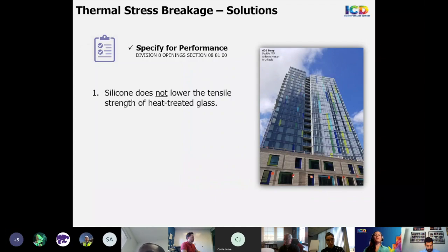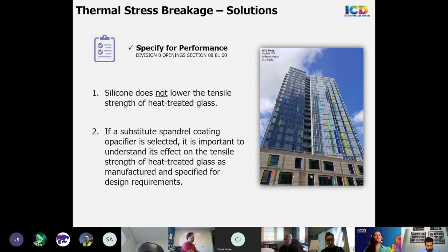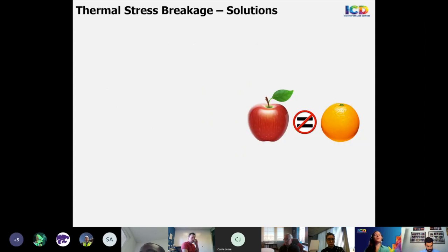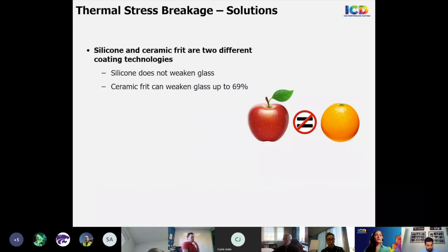So specifying for performance, specifiers can note that silicone does not lower the tensile strength of heat-treated glass, and if a substitute Spandrel coating is selected, it's important to understand its effect on the tensile strength of heat-treated glass. So I always just like to point out this reminder because there still are misconceptions out there that silicone is a Frit. So just like to remind that it's a completely different coating technology.